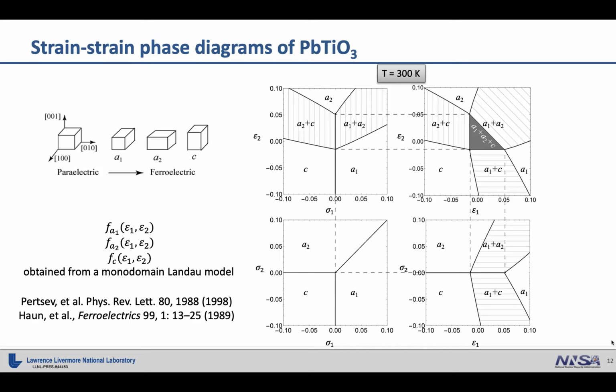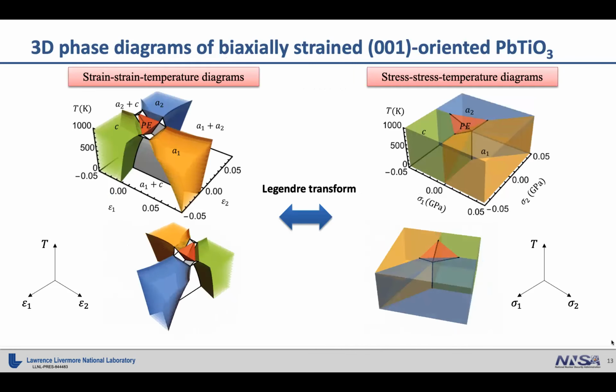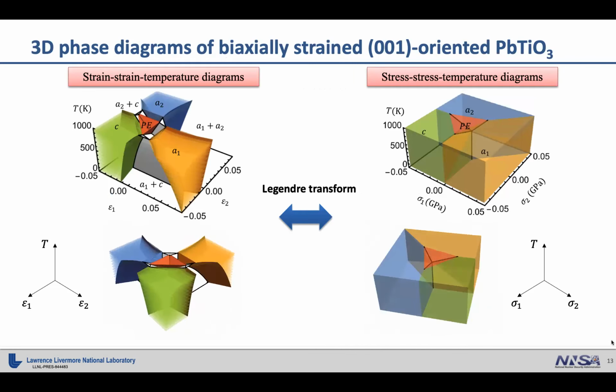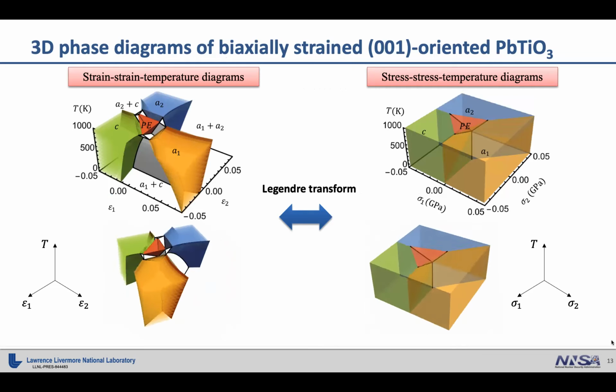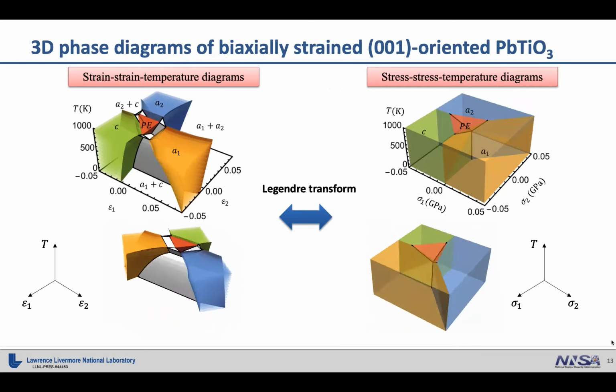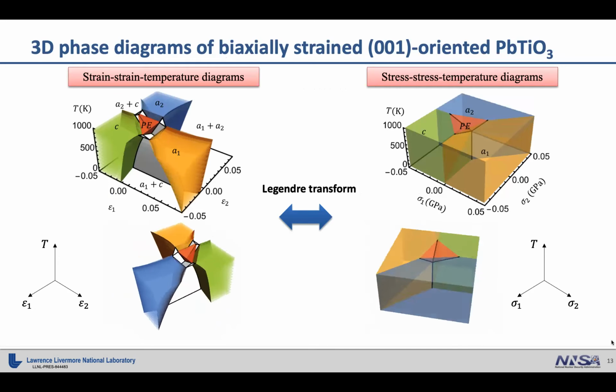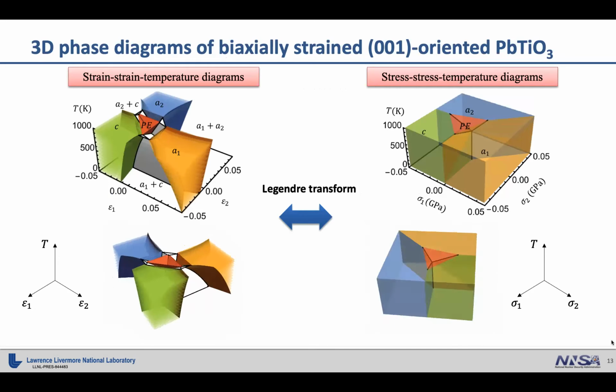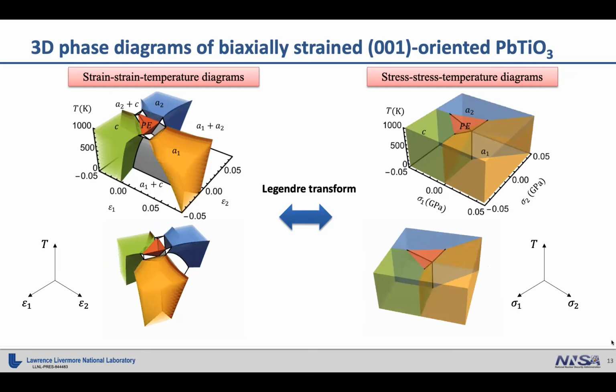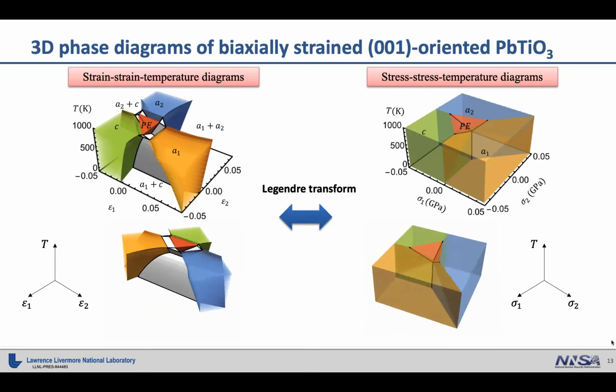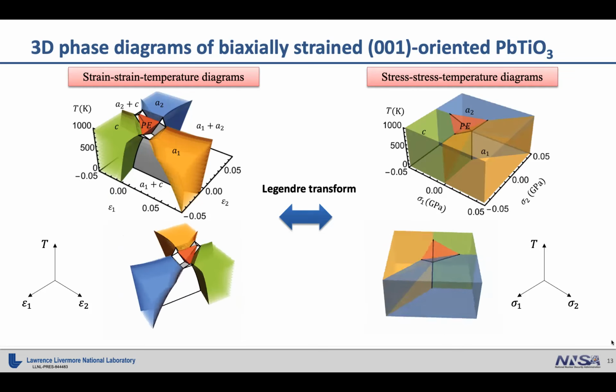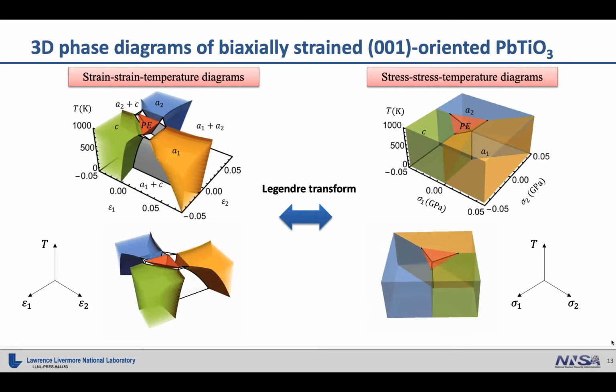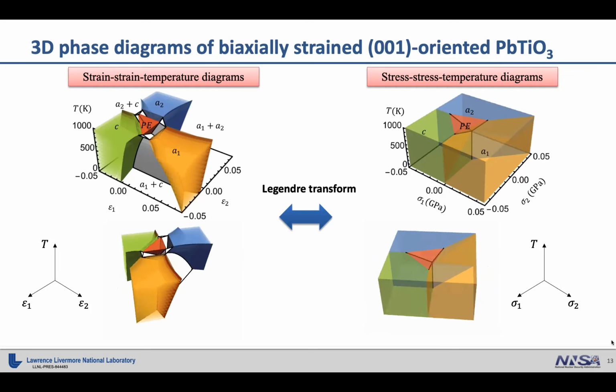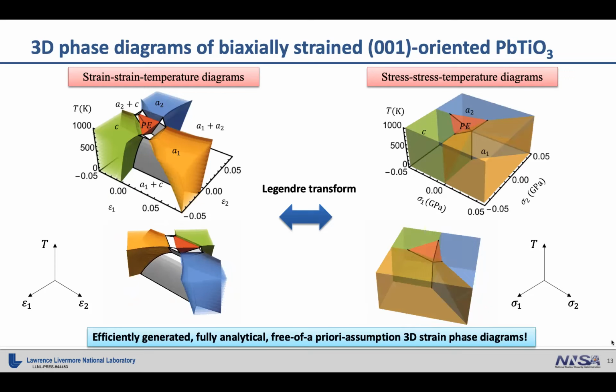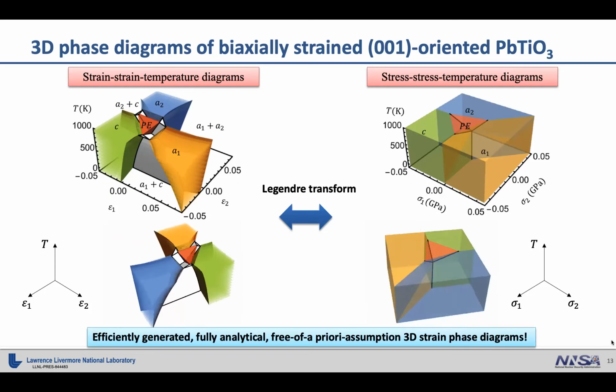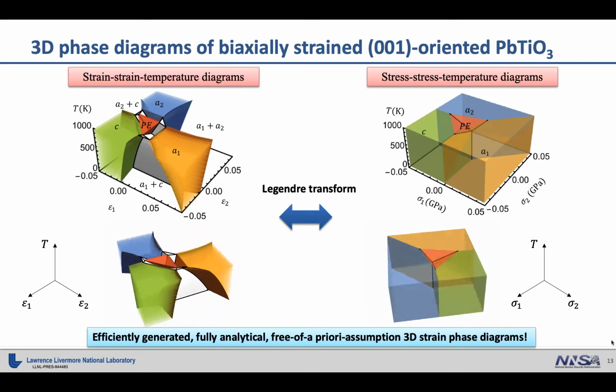And we then do a sweep of the temperature, which allows us to construct this 3D temperature-strain and temperature-stress phase diagram of the 001 oriented lead titanate. And because of the simple model we assume, it's actually quite fast. It just takes a few seconds, and I suppose that's due to the visualization of these phase diagrams, not the calculation part. It's actually all of the phase boundaries and phase regions, and we can obtain fully analytical expressions for them.